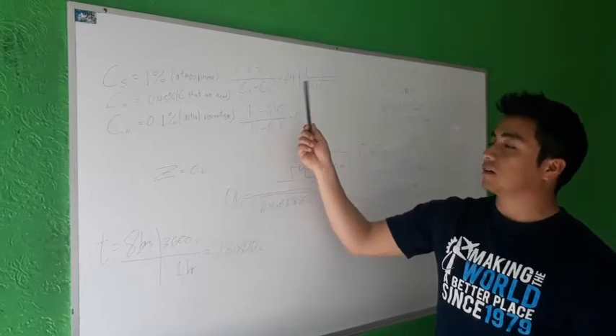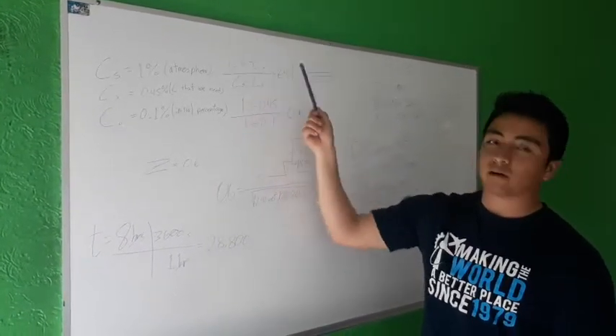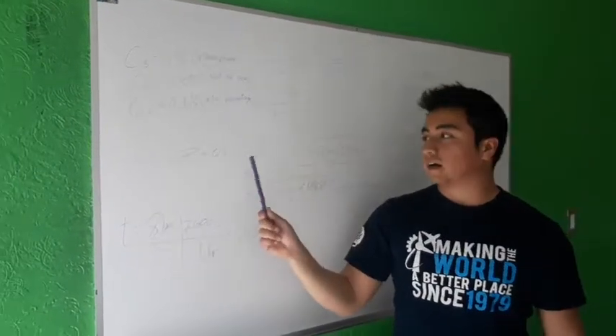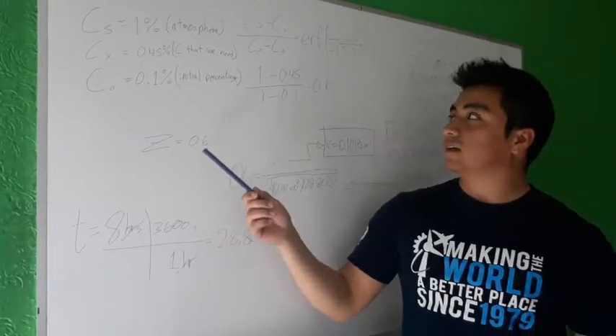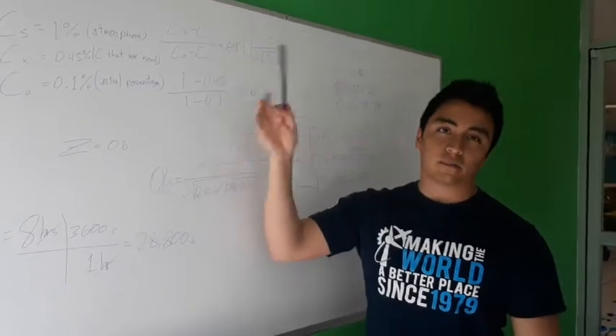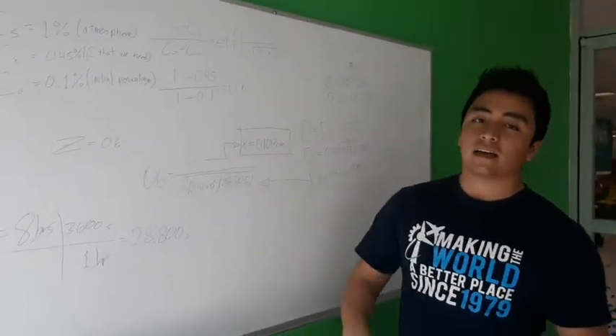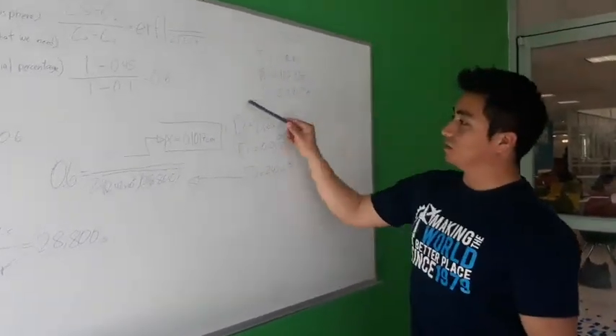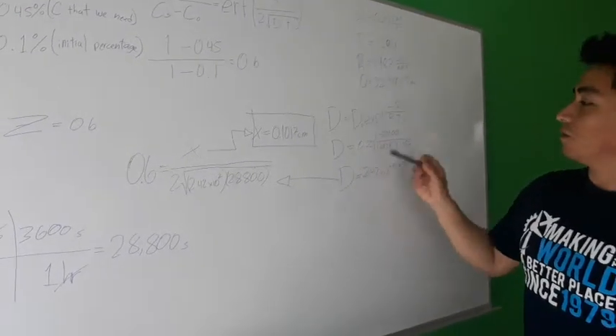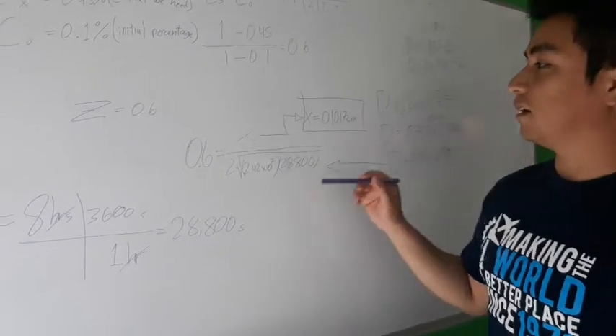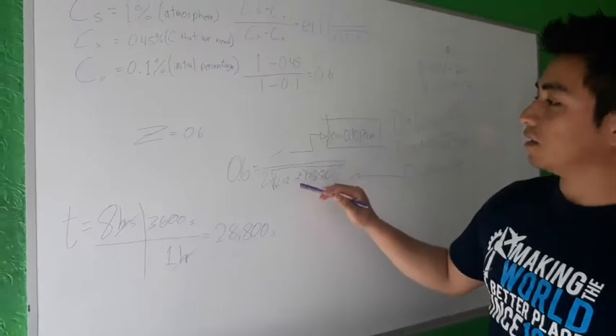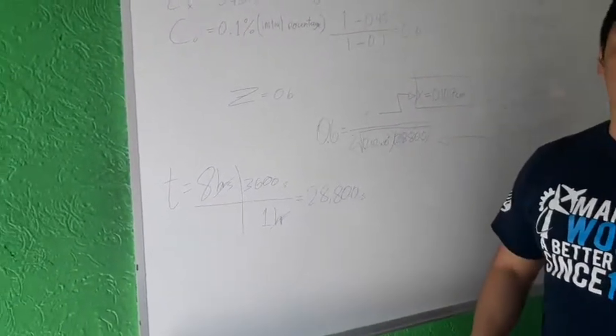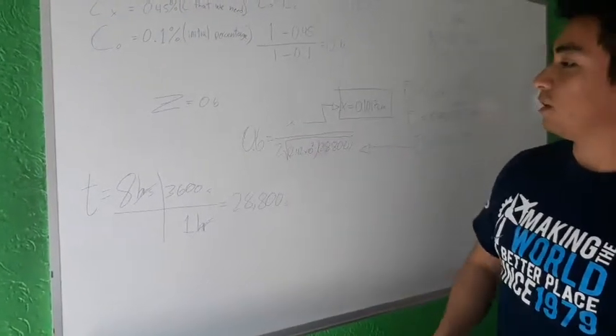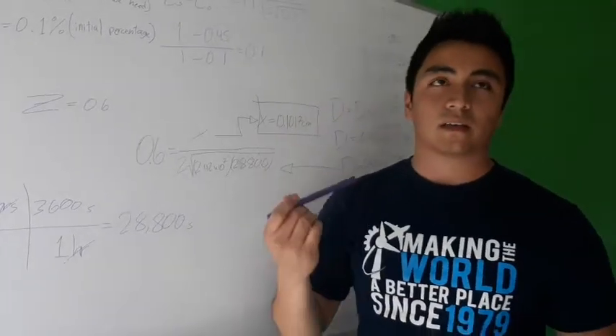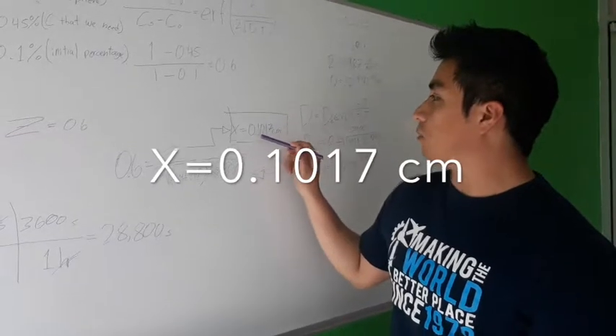Now we substitute here, and for the left part of the formula we got 0.6. Now we want to complete the other part of the formula. So we need the diffusion, and the diffusion formula is this one, and we have these parameters. We solve for diffusion, and we replace the result in the original formula, the first one that we are using, and we solve for X. So our final result is that our carbon layer depth is 0.1017 centimeters.